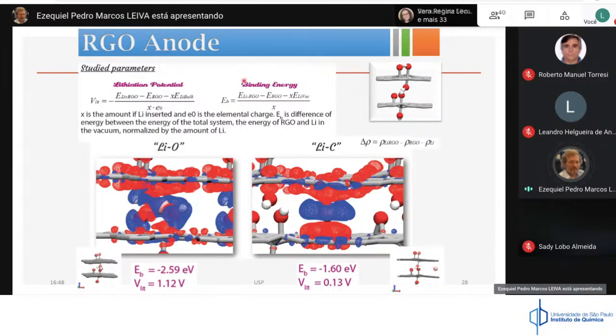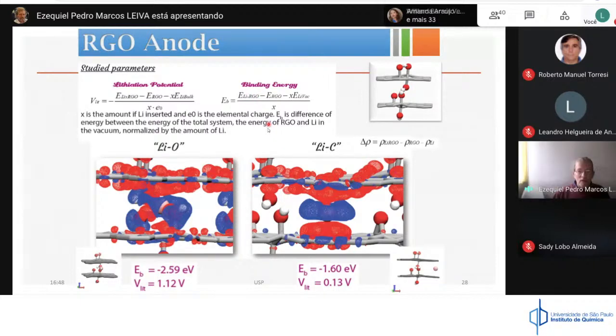One is the binding energy that tells you how strong is the interaction of lithium with this type of structure. You have to calculate the energy of the whole system, and subtract the energy of the substrate and the energy of lithium. And you get an idea of the binding energy.